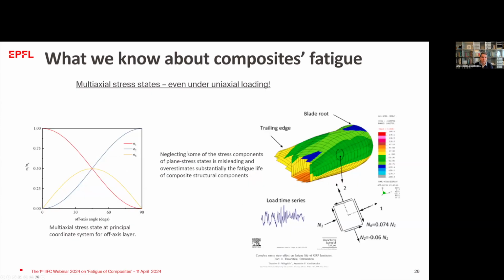So what we also know about composites is that we have to use multi-axial stress states. Even in uniaxial loading, when we have an off-axis material, we can simply calculate the multi-axial stress field in the material itself, which means that even for uniaxial loading, we have multi-axial stress states. And actually, it was around 20 years ago that we introduced this concept, and we actually somehow imposed the change in the design codes for wind blades, for example.